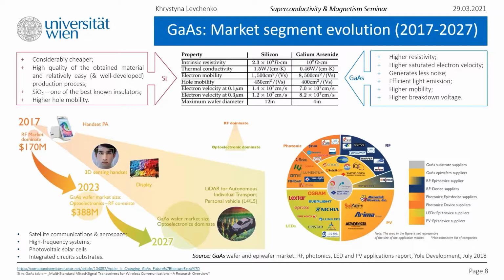It has a higher saturated electron velocity and higher electron mobility. That is, you can shoot electrons across a transistor faster, get higher gain and higher bandwidth out of transistors, and get better conduction with lower doping levels. Also, the thermal conductivity is lower, as you may see. As a rule of thumb, lower is better because then the material conducts less heat energy.